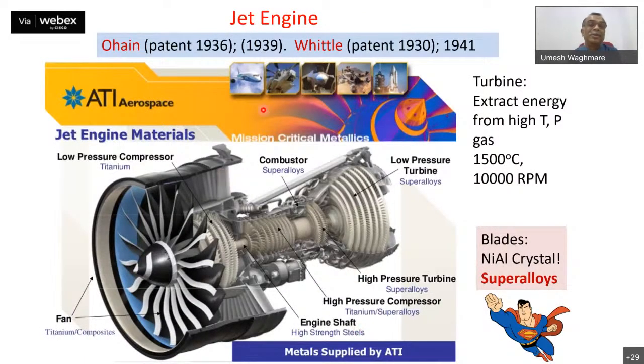The last example I'll give you from history, again just before 1950, is the jet engine. This engine is an absolutely marvelous example of how materials impact a technology. I won't go into all the details, but would like to point out that here is a jet engine blade, which operates at very high temperatures, 1500 degrees centigrade. That's very close to the melting temperature of the alloys that are used. Specifically, what is used in blades is actually single crystal super alloys of nickel and aluminum. These alloys are called super alloys because they retain their strength all the way up to 80% of the melting temperature.